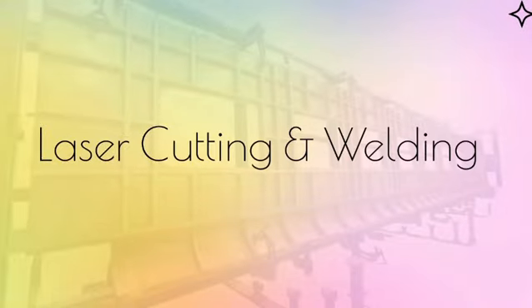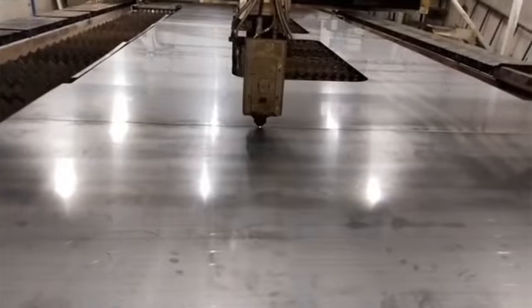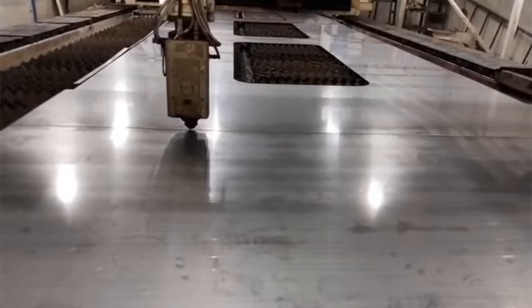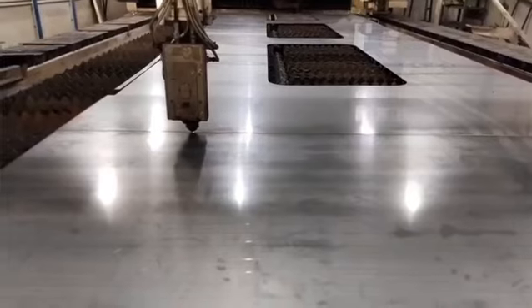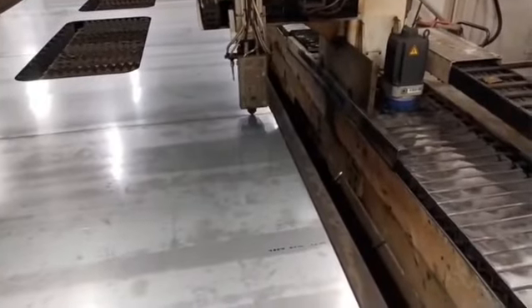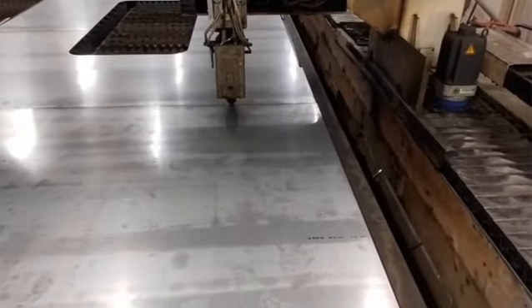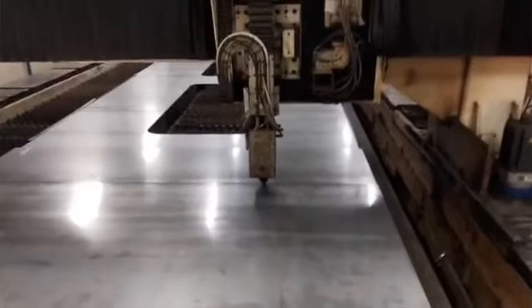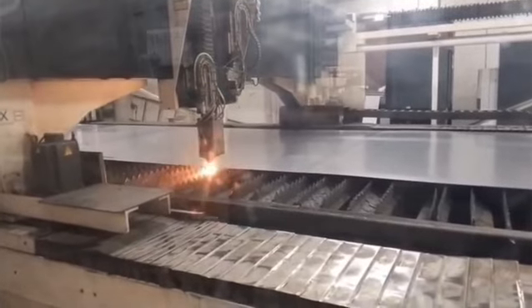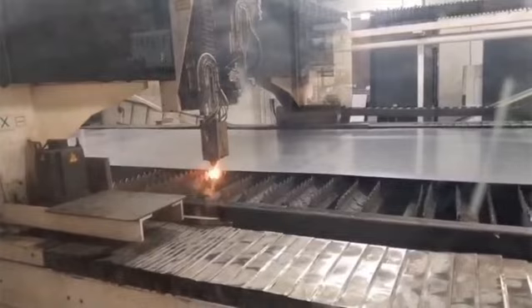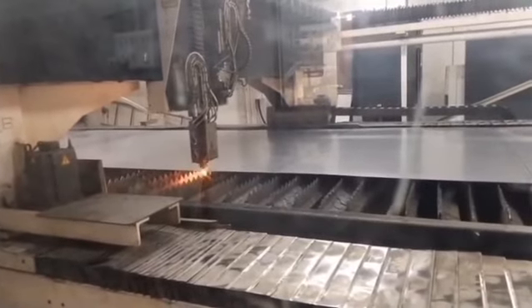This is the laser cutting and welding machine used for cutting and welding of raw steel sheets simultaneously. It joins ferritic steel sheets of thickness 3 mm used for Vande Bharat sidewall by means of laser beam welding, in which nitrogen is used as a shielding gas with a gas flow rate of 35 to 40 liters per minute. The type of joint formed by this welding is a square butt joint. In this machine, tack welding is also laser welding.